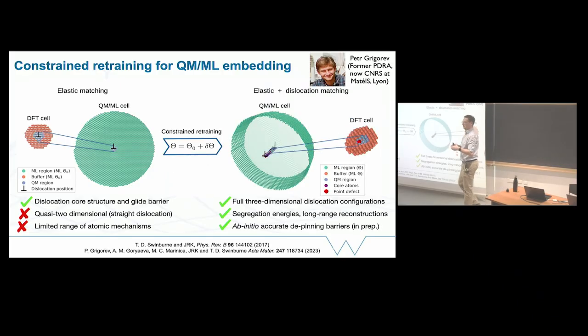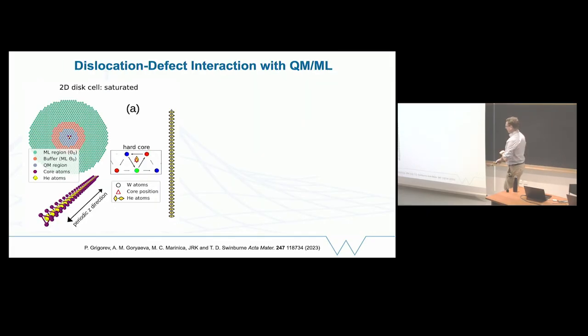So our potential is now good enough that we can make a big 3D system. The dislocation is described well there. And we only treat, for example, an impurity with quantum mechanics. So we need a small spherical region with a helium in it. We don't need a ginormous sausage treated with high precision method. And this is something that Petr has been working on for a few different applications. So this is the one I had in mind. If you put things in 2D, then effectively if you put a defect in, you don't have one defect, you have a big stack of defects. And that's not really the relevant regime if you have only a low concentration of helium. You would first have one helium somewhere, you wouldn't have a big line of them.